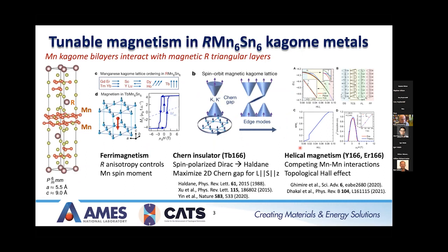So we've seen this a lot. The interesting thing about kagome metals is that you naturally get these Dirac crossings at the K points and flat bands. The trick is getting these interesting features in a real material near the Fermi surface so that you can actually observe something. So a lot of these materials, a lot of the heavy rare earths order in a ferrimagnetic structure. So you have the manganese, so the kagome layers are always ferromagnetically aligned.